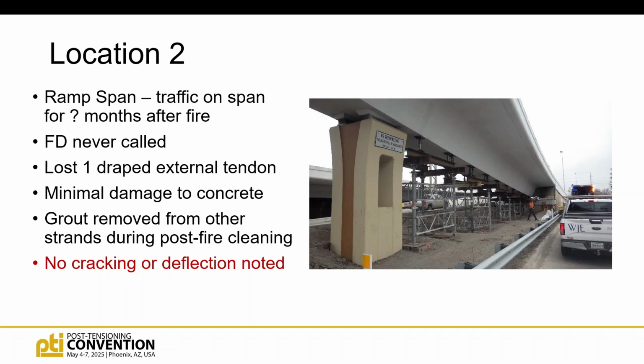They did lose one external tendon, but the other 3 remained in place. Similar to the other span, there was minimal damage to the concrete. And I'll show you some images, and if you see grout that was removed, that was done during either our assessment or by the DOT's cleanup crew, but all the grout remained intact on the intact tendons. And once again, no cracking, no deflections, no external evidence of any type of distress to this span.